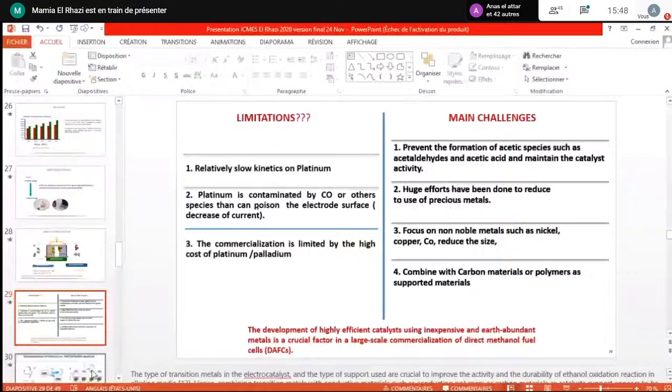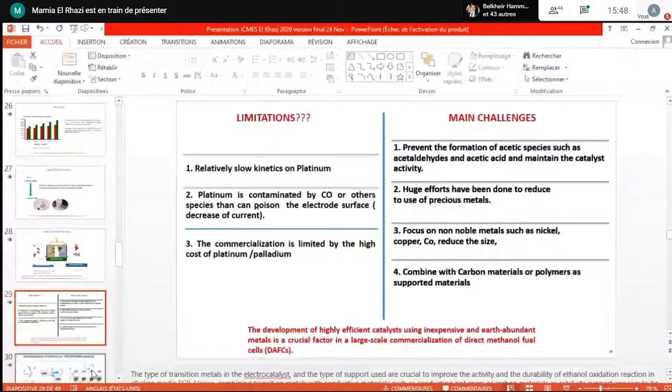The nanocomposite catalyst support was prepared on a carbon-based electrode using the direct electropolymerization of paraphenylenediamine monomer on a drop-cast carbon nanofiber network. Afterward, the copper dendrites were electrodeposited on the nanocomposite in potentiostatic mode.